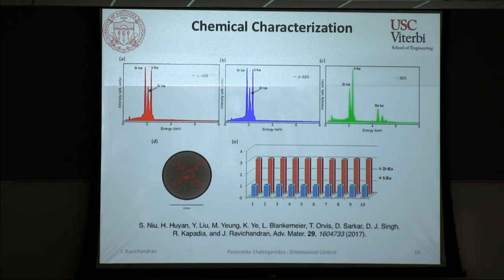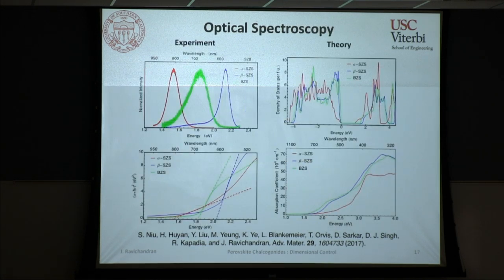So the most important thing is to look at optical properties of these materials. This is a busy slide, so I'm going to start with the right side. These are theoretical predictions of the density of states for the strontium zirconium sulfide alpha phase, strontium zirconium sulfide beta phase, which is the corner-shared perovskite, and barium zirconium sulfide. And using the density of state values that we obtained, we were able to predict the absorption coefficient, and hence the band gap values for each of these 3 phases.